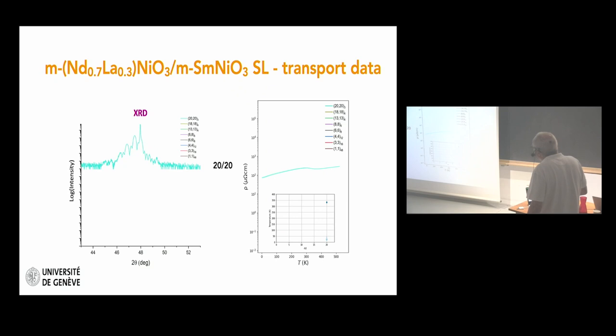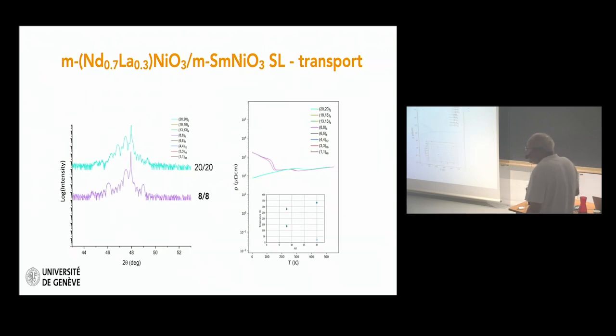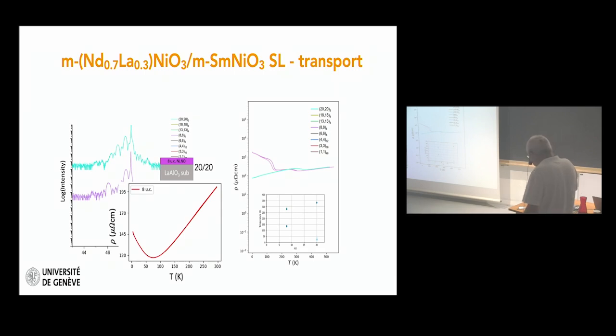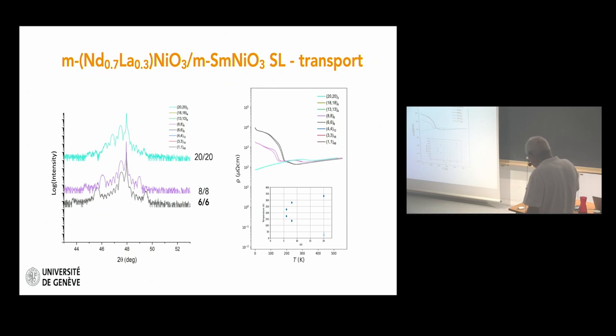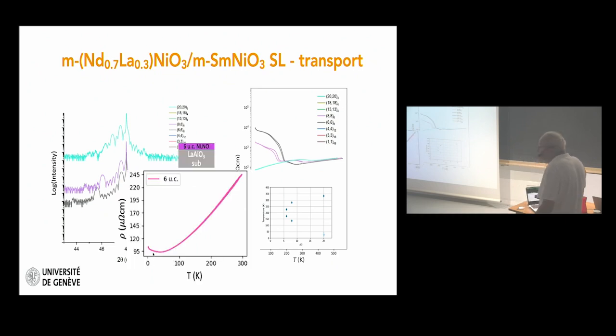So let me show you the results. Again, the characterization. This is a thick superlattice, resistivity versus temperature. And you see that it's metallic. A small bump here, the samarium nickelate layers are turning insulating, and it's metallic all the way. 8-8, now interesting, we see two transitions. So the solid solution is insulating in the superlattice, but metallic with a small upturn as a single layer. But if you look at very low resistivity, 6-6 again, two transitions, still metallic. And so we believe that indeed here, this phase boundary cost has pushed these metallic layers to be insulating.